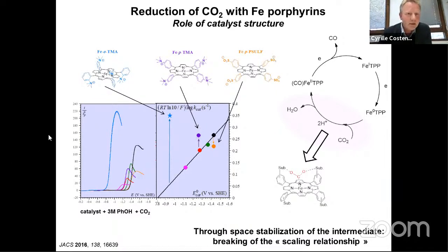The idea here is to introduce either a positive charge on the catalyst or a negative charge on the catalyst. The idea is that with those positive or negative charges on the catalyst, you may stabilize or destabilize the intermediate in the process, because as I said previously, when CO2 binds to the iron, you sort of push electrons to CO2 and you put those electrons on the oxygen. And so if you have a positive charge here, you may stabilize this intermediate and so boost the catalysis. And this is exactly what is observed here.